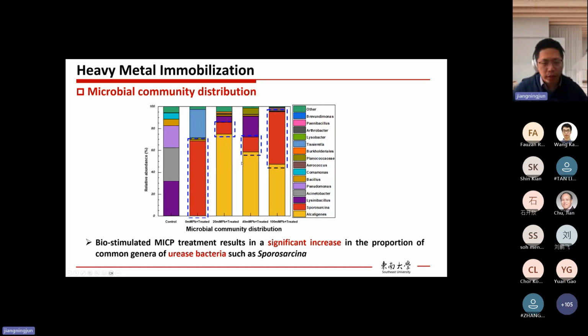So this one, after we analyzed it, we found it's a lead-resistant species. So that's why when we have lead, it becomes dominant. However, if the lead concentration becomes even higher, then this part becomes smaller. Then, in contrast, the portion for Sporosarcina becomes larger again. So we guess that where we have a lot of lead contaminants, this one is not as resistant as Sporosarcina. So that's why Sporosarcina becomes dominant again under this condition.